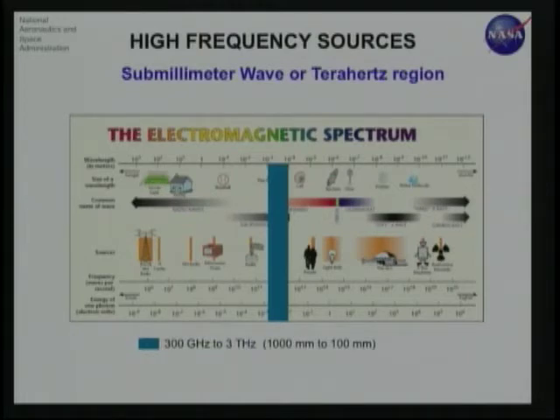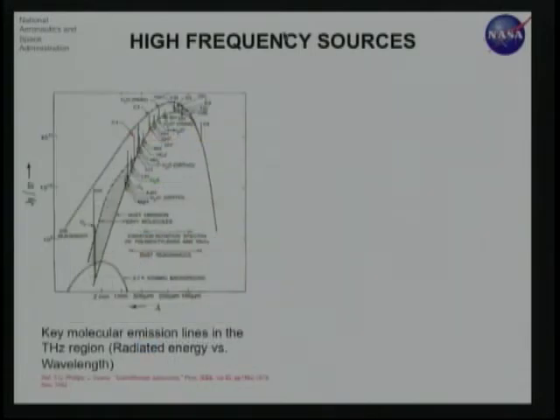But this is very important because 300 gigahertz to 3 terahertz, corresponding to 1 millimeter to 100 micron wavelength range, has a lot of emission spectra. This is one of the old graphs developed, reported in Tom Phillips' paper, showing that 300 gigahertz to 3 terahertz corresponds to a black body temperature of 14 to 150 Kelvin. So here is a 30 Kelvin black body.